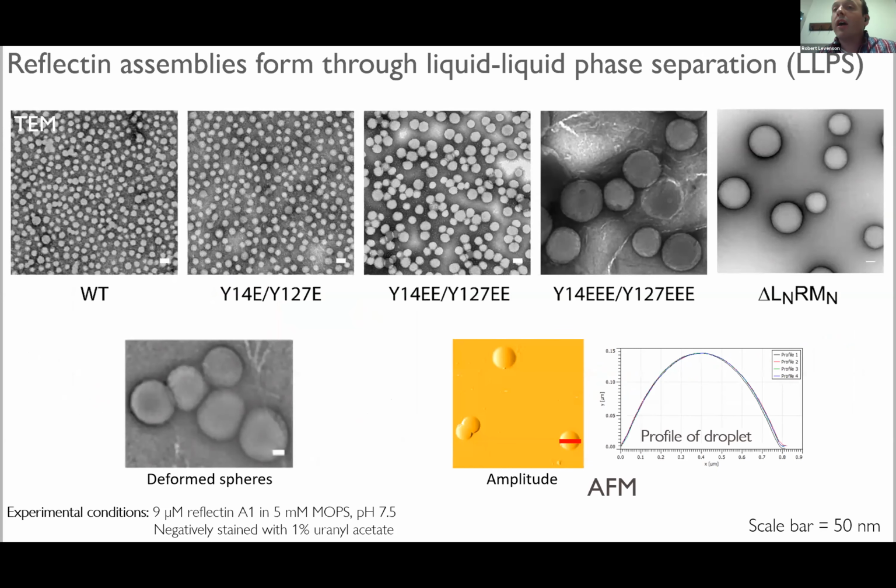Electron microscopy or atomic force microscopy characterization of these assemblies shows that they are spherical, particularly at the large size range. It's highly spherical. Clusters of particles can sometimes be observed, and they undergo deformation. It's soft matter that we are assembling here. And the very high degree of sphericity that we see in these assemblies strongly suggested to us that there's some kind of a liquid state, either transient or not, involved in the assembly process, followed by dynamic arrest to give us the size stability that we see in our tests.